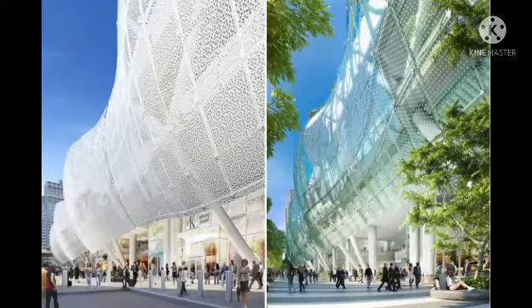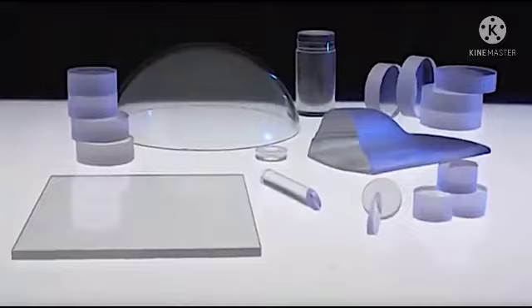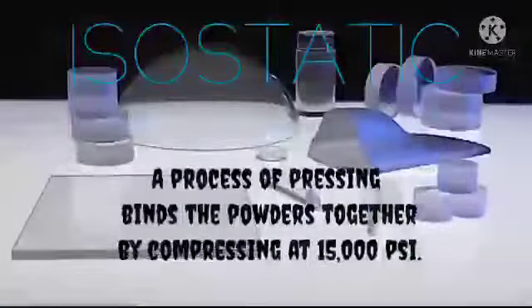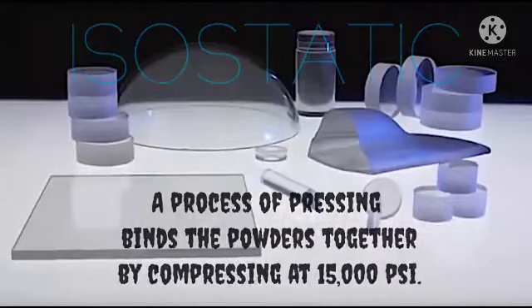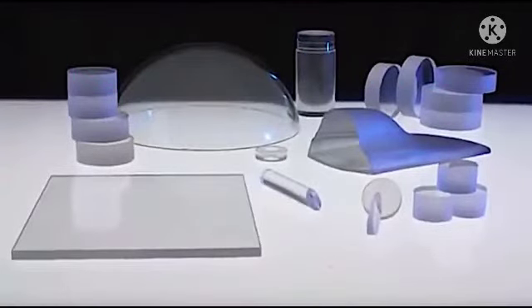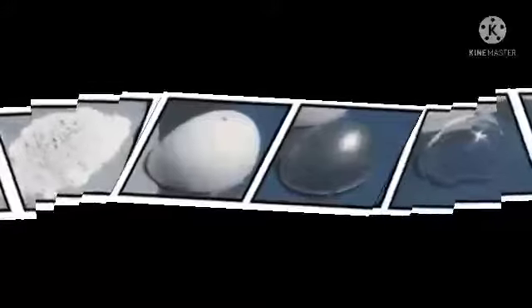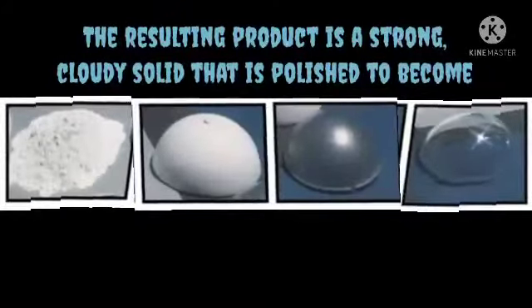Transparent aluminum is manufactured by sintering. Fine powders of aluminum oxynitride are packed into a rubber mold. Usually, these molds are in the shape of a half sphere. A process called isostatic pressing binds the powders together by compressing at 15,000 psi. Then, the compressed form, called a green body, is heated at 2000 degrees Celsius for several days. This further fuses the powders together. The resulting product is a strong, cloudy solid that is polished to become transparent.